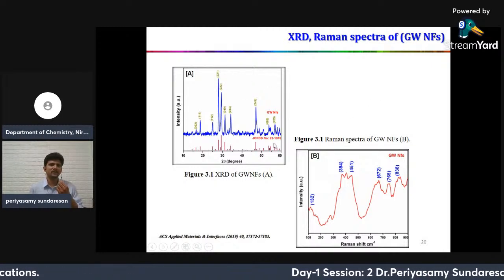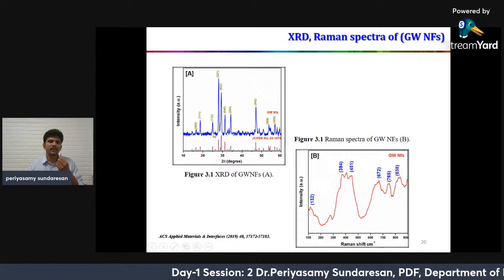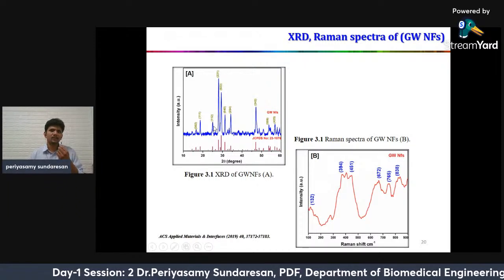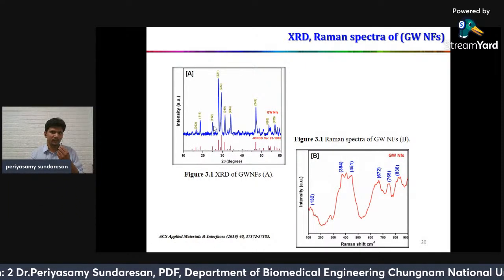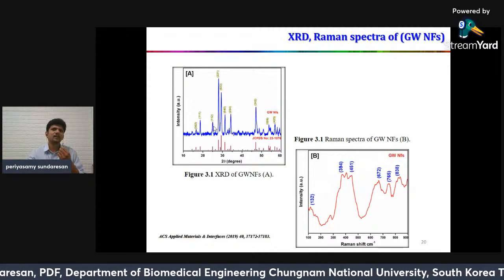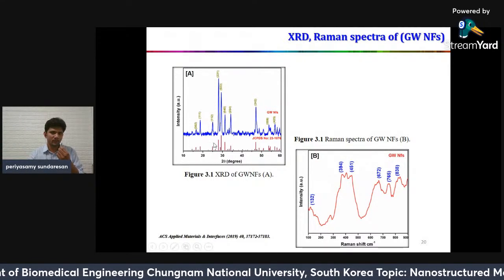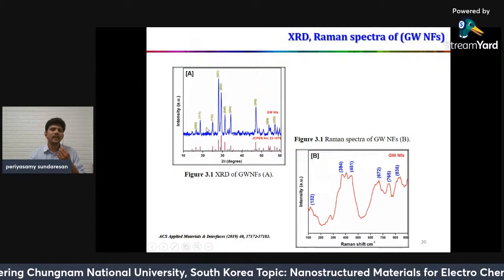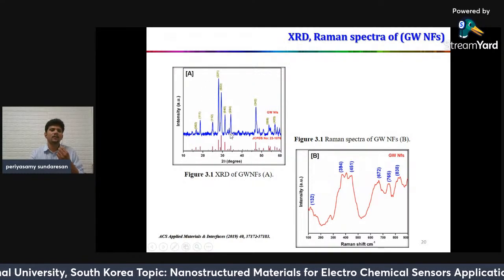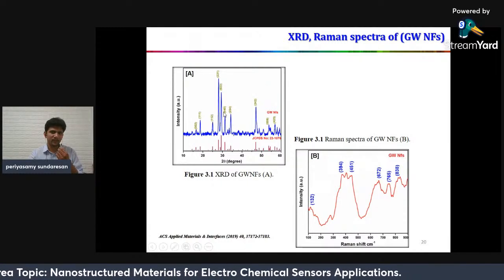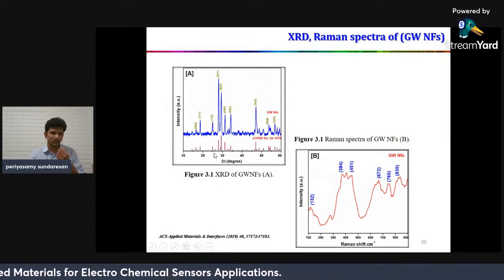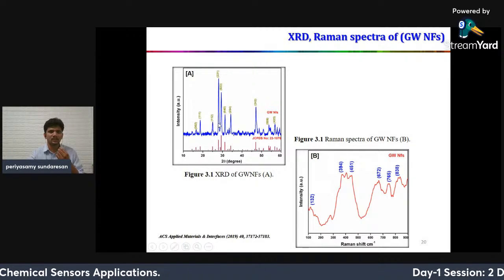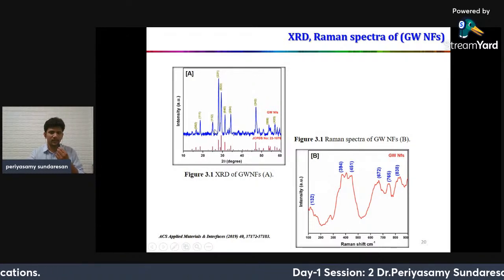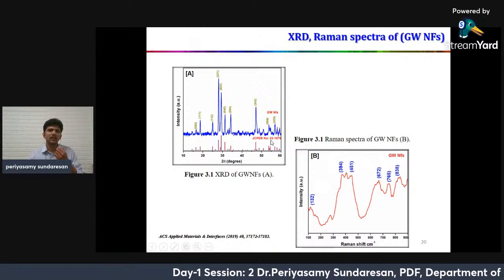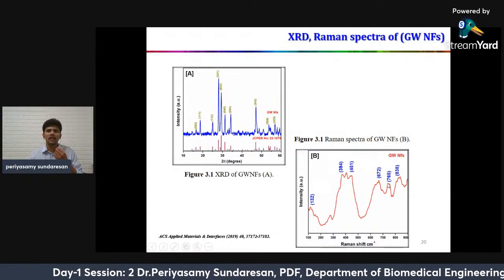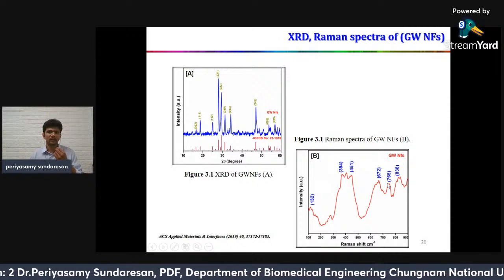This is XRD structures of the prepared catalyst. Here, the prepared catalyst is studied with X-ray diffraction. If your compound is more crystalline, we get a more intense peak. Here, I get the most intense peak for the gadolinium tungstate group at 28.5 degrees, and the prepared catalyst was checked with the JCPDS file. It has a more crystalline structure, and the Raman spectra also confirm the presence of the element.